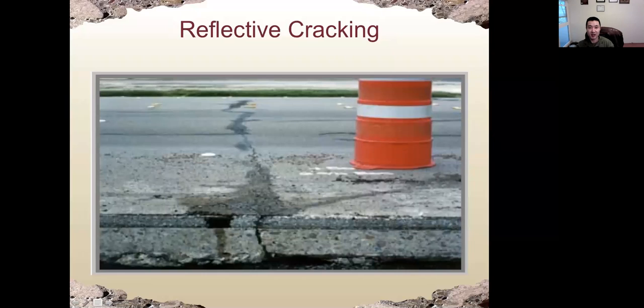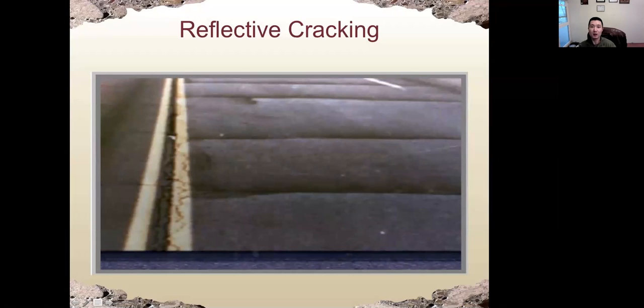And this is another type of crack called reflective cracking. In this asphalt concrete, we have two layers. The top layer is made of asphalt, and the bottom is made of Portland cement concrete. So when we have Portland cement concrete underneath, the Portland cement concrete may crack due to many different reasons, and that will transfer the cracking into the top asphalt layer. So we call that reflective cracking. Here is another picture of reflective cracking, and we can see above the joint of the Portland cement concrete, we have this cracking above that joint.